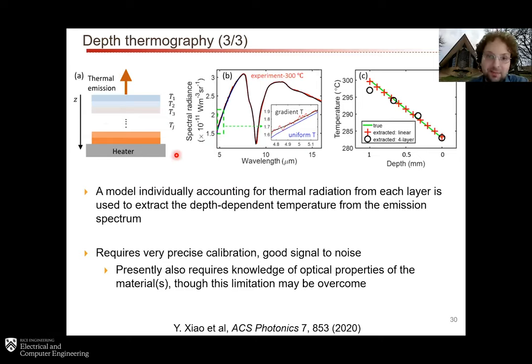Once we've obtained the measurement, we build a model, which is essentially, in this case, just one solid block of material. This is just fused silica, but we're saying that it's made up of a bunch of different layers, and each one is at a slightly different temperature. We can use the fluctuation dissipation theorem to calculate the total thermal emission from this object, which is now a non-equilibrium object because you can't assign a single temperature to it. Each layer has a different temperature and each layer is semi-transparent.